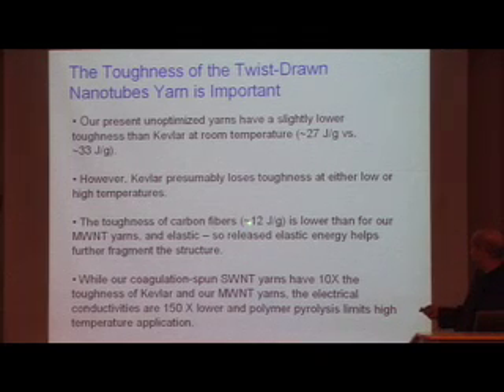The toughness of carbon fibers is about 12 joules per gram. If you take a tow of carbon fibers and try to break it, you never could break them. You tie a knot in it, it just breaks so easily. Again, showing its vulnerability to knotting.